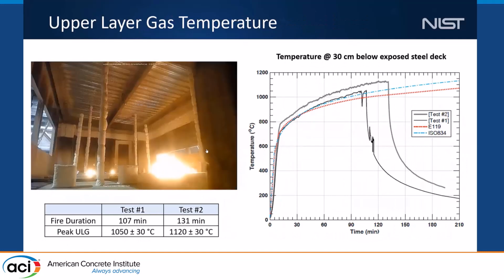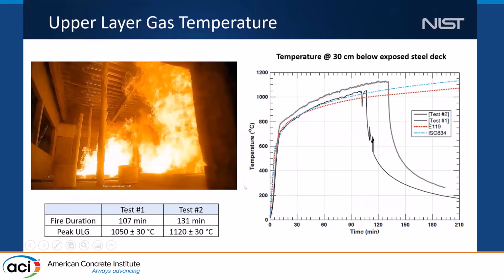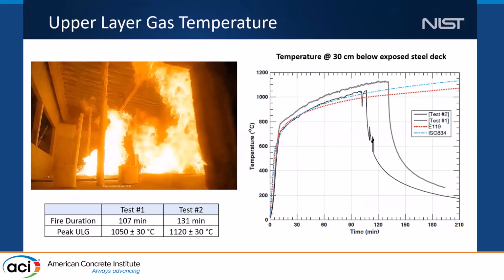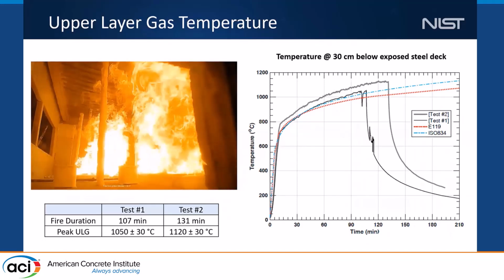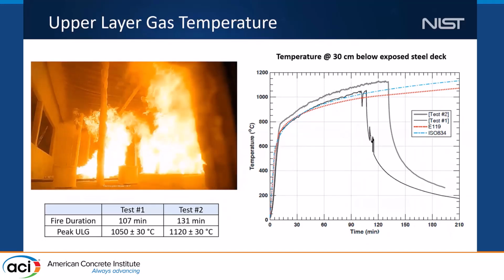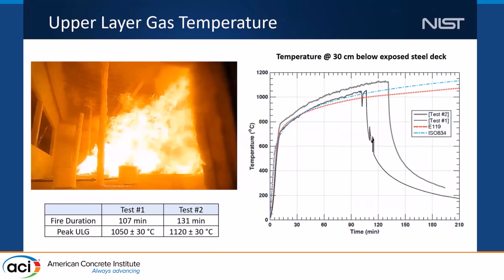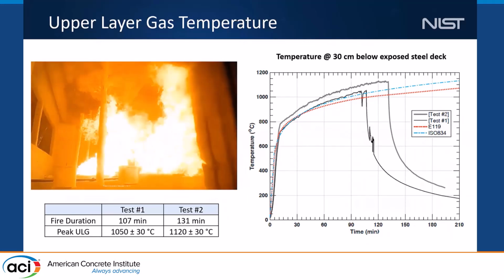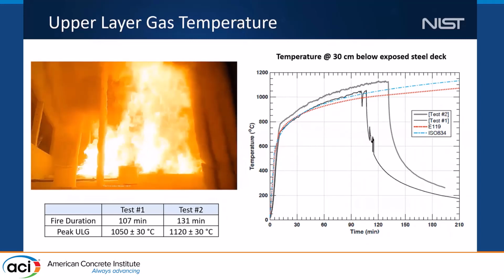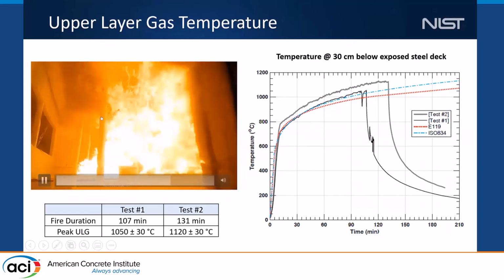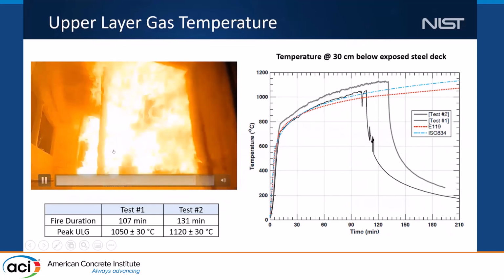So this test video basically shows the fire inside of the test compartment. As you can see here, it creates very intense, extreme heating conditions such that the upper layer gas temperature was in excess of 1,000 degrees Celsius. But since we did a special compartment design, considering the ventilation, thermal properties of the exposed wall, and distribution of the burners, the upper layer gas temperature was pretty uniform across the test bay, with a standard deviation of about 30 degrees Celsius.